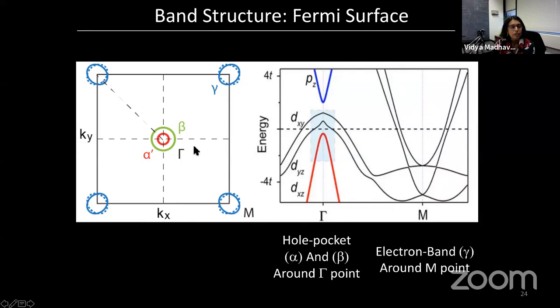So the band structure of the material looks like this. This is the Brillouin zone. You have a few different pockets. You have these alpha, beta, and gamma pockets at different parts of the Brillouin zone. And if you look at the gamma point, you have multiple bands crossing the Fermi energy, but the band inversion occurs between these two bands.